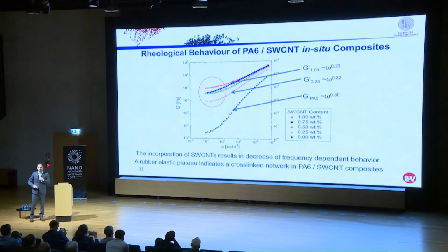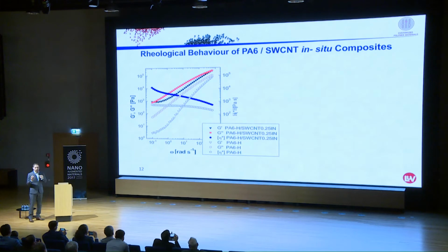Let's go a little bit deeper into the rheological behavior of the material to show you how big the effect is. What we see here is the oscillation frequency against the storage modulus and the loss modulus, and on the right scale it's the viscosity. Let's start with the viscosity of PA6, the non-filled symbols here. PA6 behaves like a Newtonian fluid, basically. And with 0.25% of TUBALLs inside it, incorporated with the in-situ technique, it behaves like a cross-linked network. So it shows a shear thinning effect. The viscosity is now dependent on the shear force.